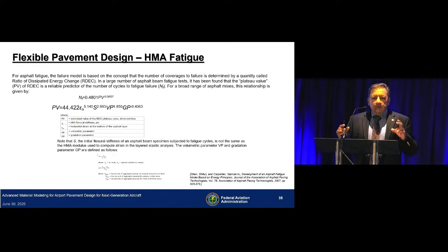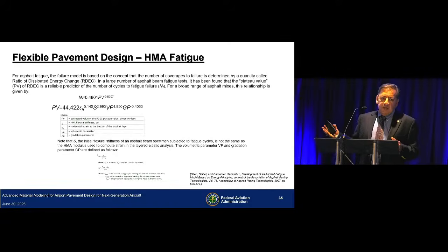So what this design procedure does is measure the flexural stiffness of the beam for the first 100 repetitions, and failure is considered when the stiffness reaches 50% of the initial value, which signifies formation of microcracks in that asphalt beam. And the void parameter and gradation parameter are coming from your mix components. So if you know what asphalt mix you have, you can compute your gradation parameter and the void parameter and compute your number of cycles to failure.